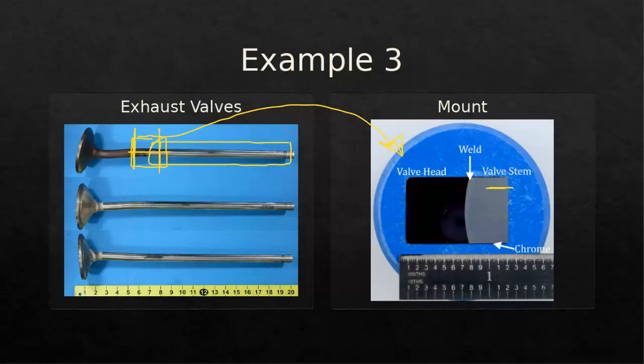So why and how were these welded together? This is 4140 steel, and it is inertia welded to a 21-12 stainless steel, which is 21 chrome, 12 nickel stainless steel. So that's why this portion of the material did not need a chromium coating. It's already going to be protected in the environment that it's in. But they wanted to look and see if there was any failures or any signs of failures within this weld zone.